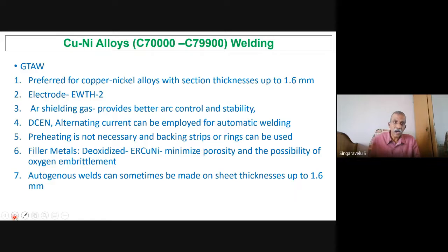GTAW of copper-nickel alloys up to 1.6 mm you can do. Use a thoriated electrode, argon shielding gas, DCEN, or alternating current can be used for automatic welding. Preheating is not required. And backing strips or rings can be used to support the root pass.